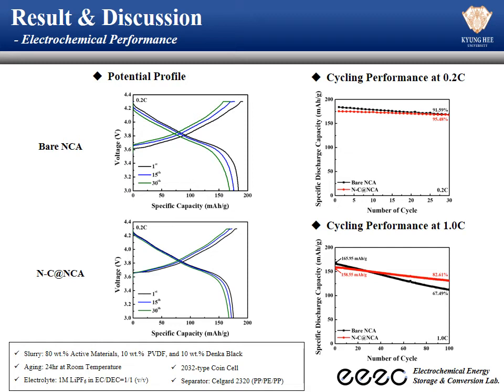Through the potential profile graph between the two samples, it was confirmed that there was no significant difference in the charge and discharge behavior between the two samples. So it can be said that the coating layer does not affect the charge and discharge behavior of NCA. And as a result of confirming the specific discharge capacity retention for 30 cycles at a 0.2C rate, it can be seen that bare NCA is higher than NC.NCA in terms of initial capacity, but after 30 cycles, NC.NCA showed a capacity retention of 95.48%, and bare NCA showed a capacity retention of 91.59%.